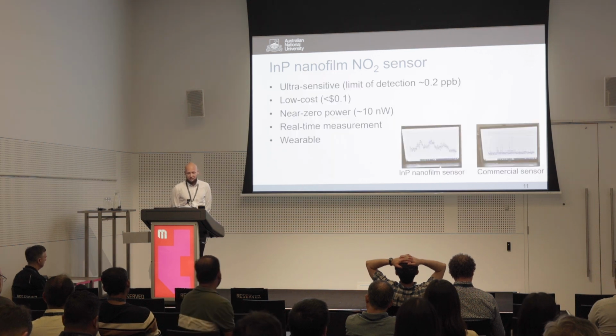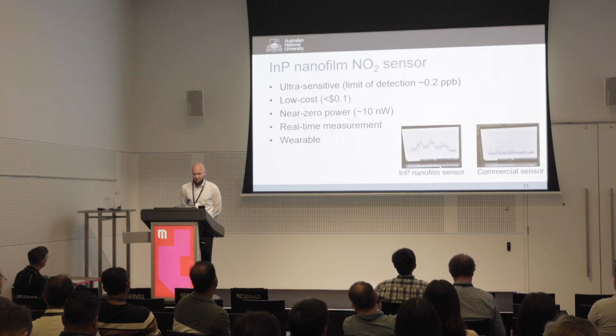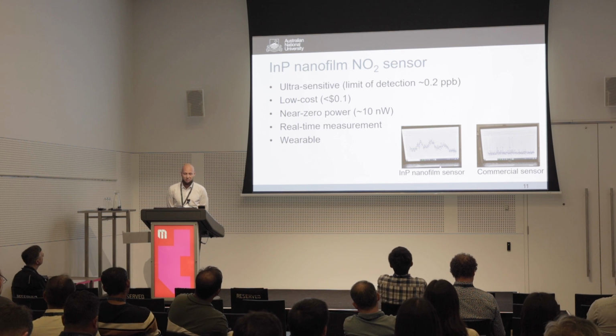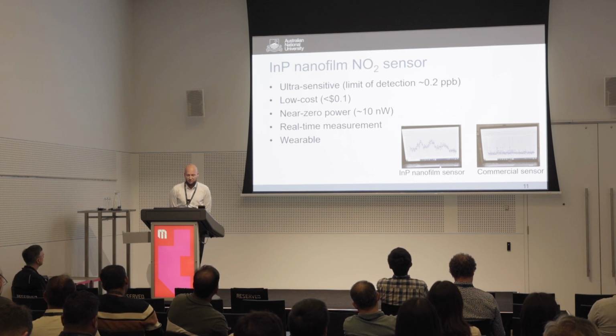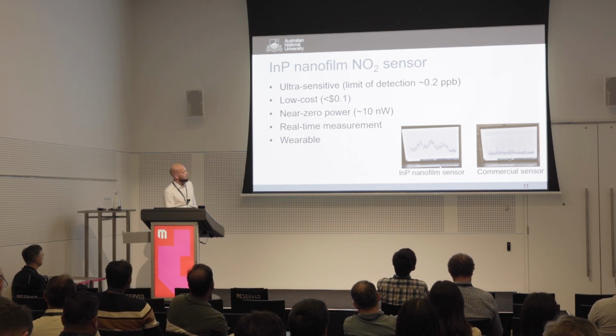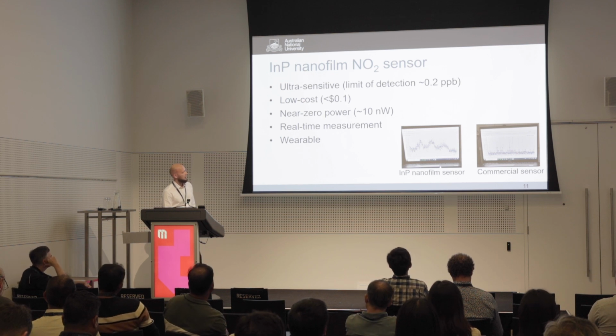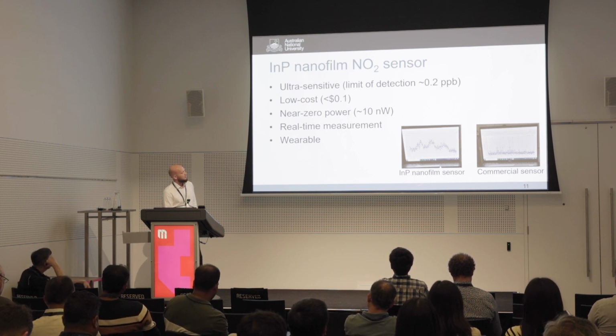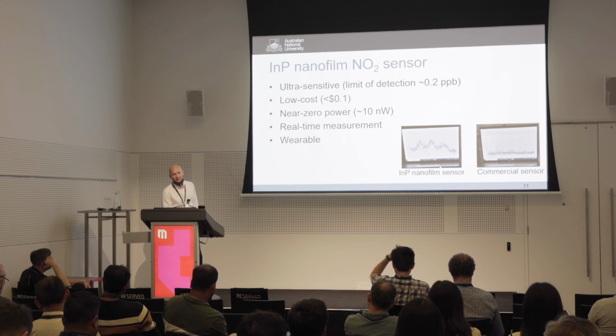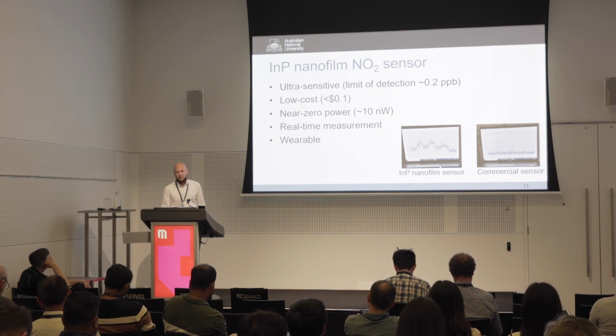Some properties of the nanofilm sensor. So it's ultra sensitive. The limit of detection is in ppb level, or parts per billion, which is quite important. As you can see here, I measured the 3 ignitions with the nanofilm sensor from the gas burner, and we can see 3 clear peaks. And then we did the same measurement with a commercial sensor, and all you can see is noise.